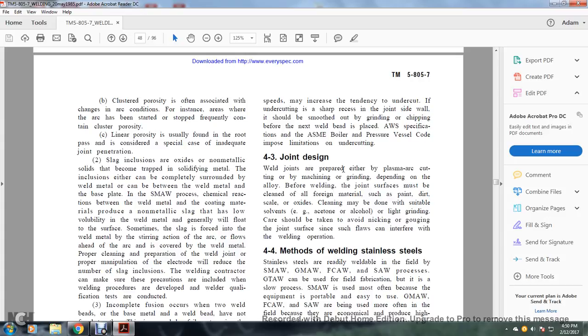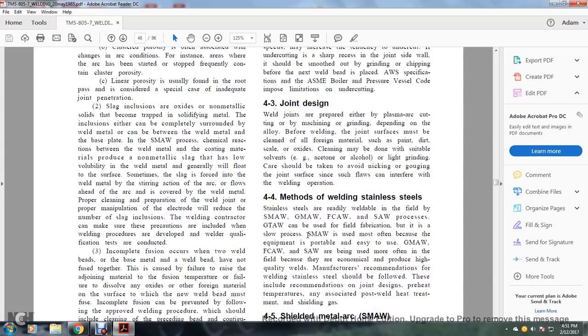Welding joints are prepared either with plasma arc cutting or machine grinding, depending on the alloy. Before welding, the joint surface must be cleaned of all foreign materials such as paint, dirt, and oxide scale. The cleaning may be done with suitable solvents such as acetone or alcohol, and care must be taken to avoid nicking or gouging of the joint surface, which could interfere with the welding operation.